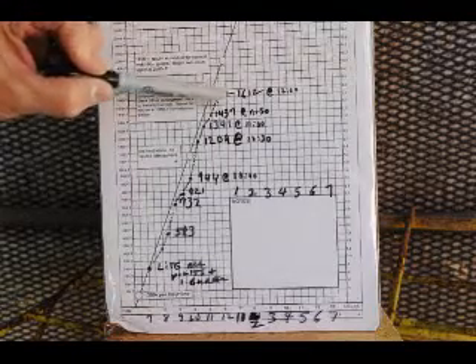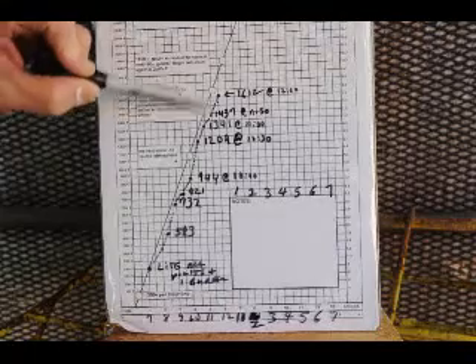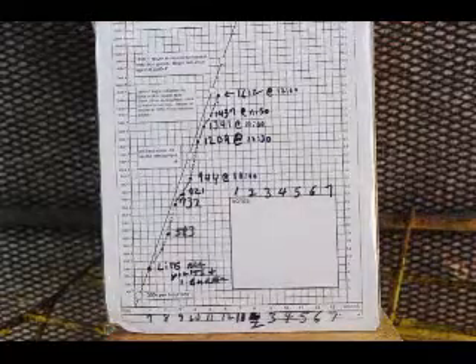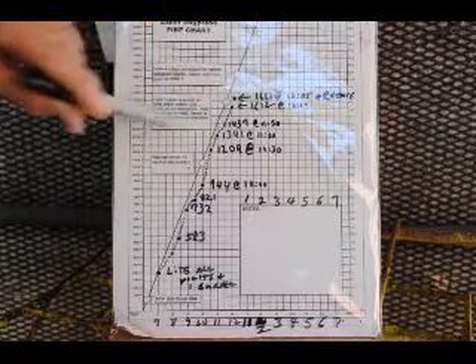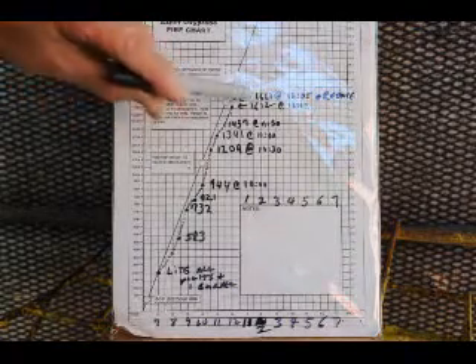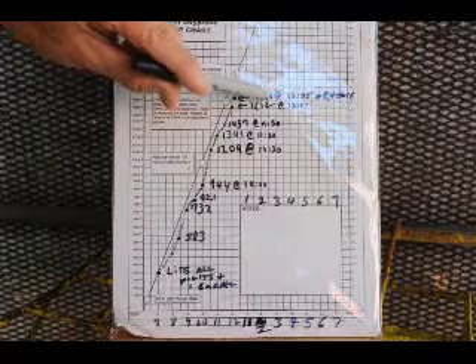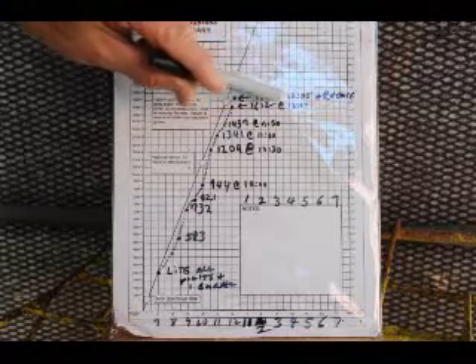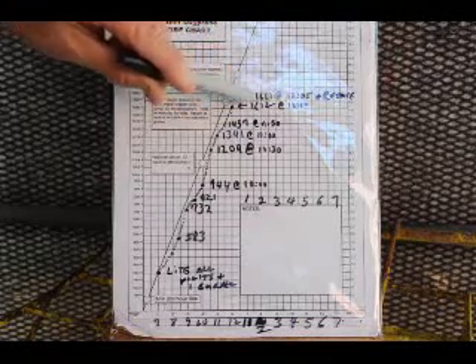It's now 12 noon. Temperature is 1612. Rate of climb is 300 degrees an hour. So we're going to leave it alone for the time being. It's now 12:05. The temperature is 1660, and we start a body reduction at 1650. So the way I'm going to reduce is instead of closing the damper a little bit, I'm going to increase the gas, which is presently running at 3 units. I'm going to increase that to 4.5 units of flow, and that will be enough gas to put the kiln in reduction.